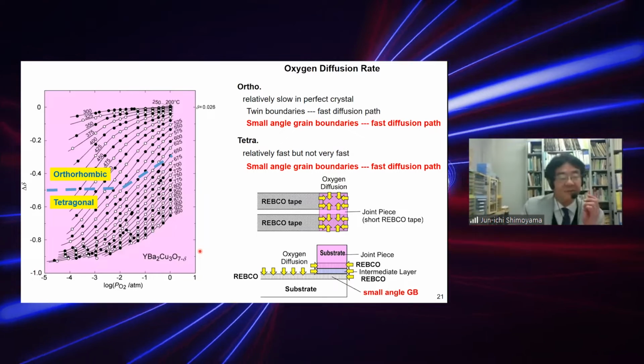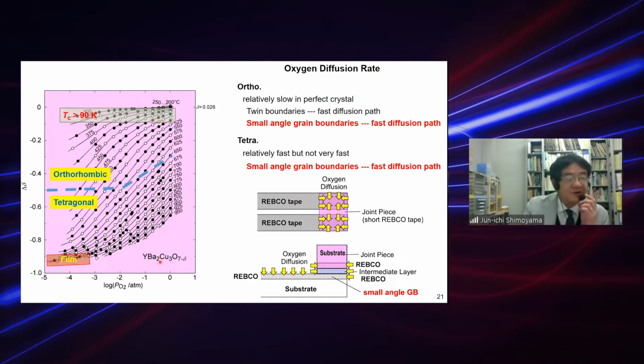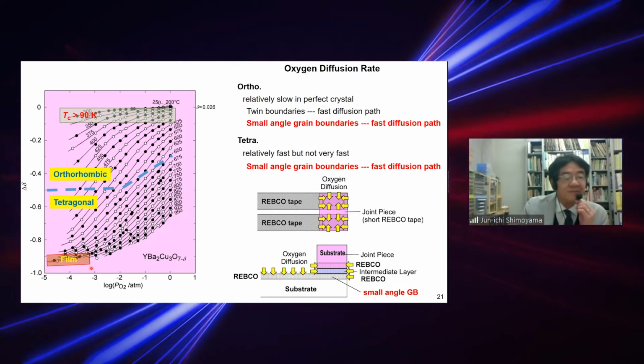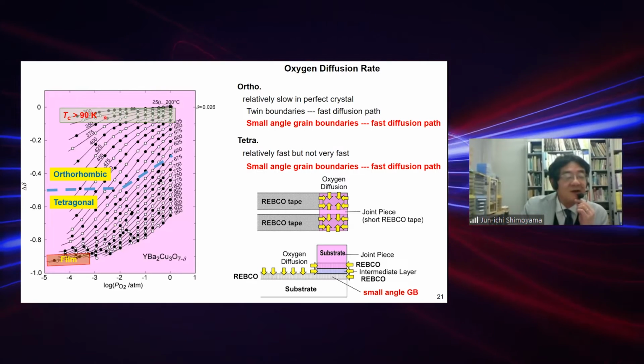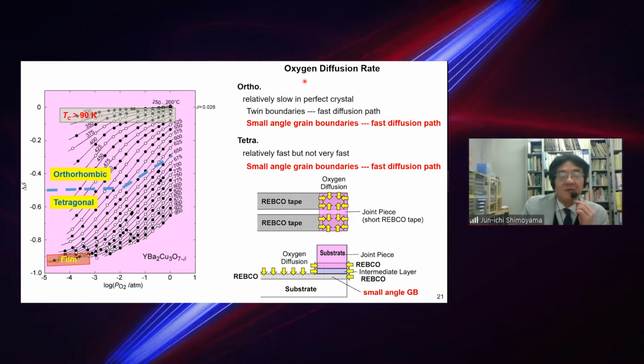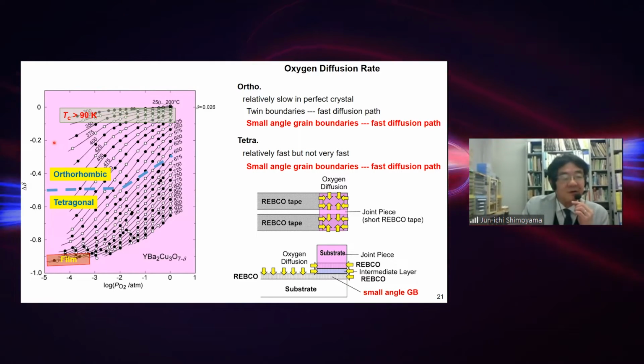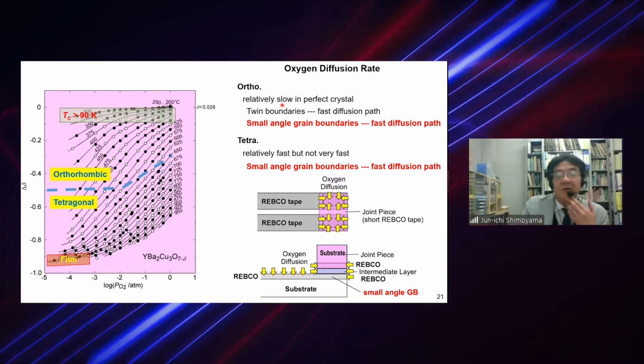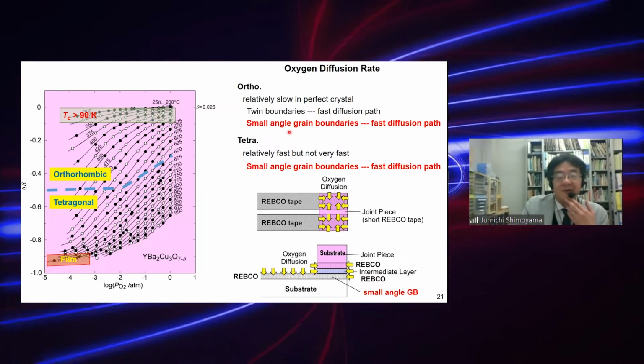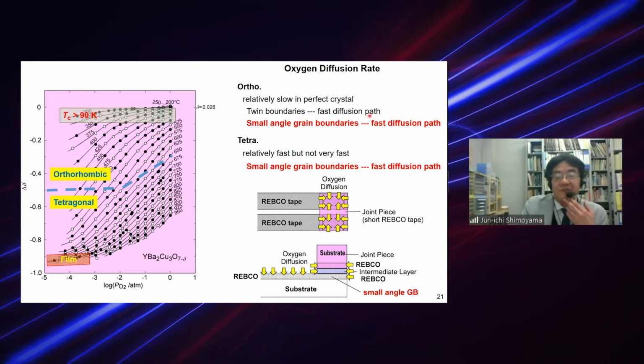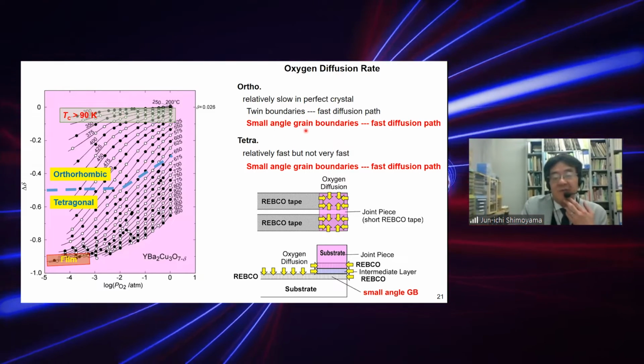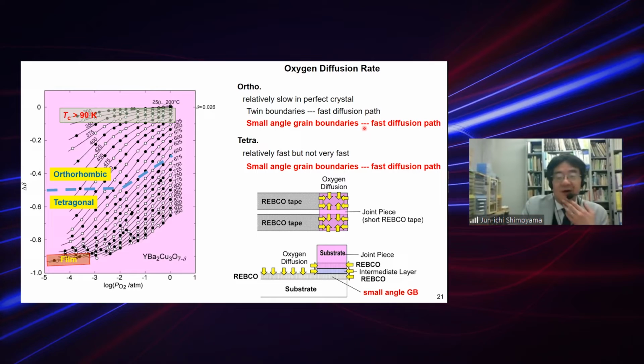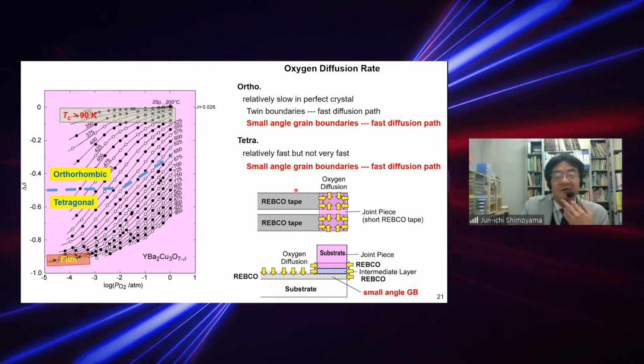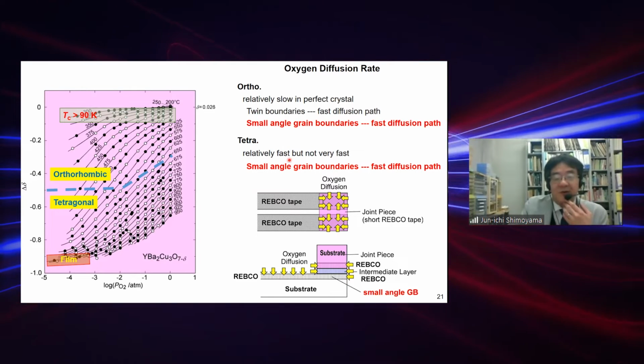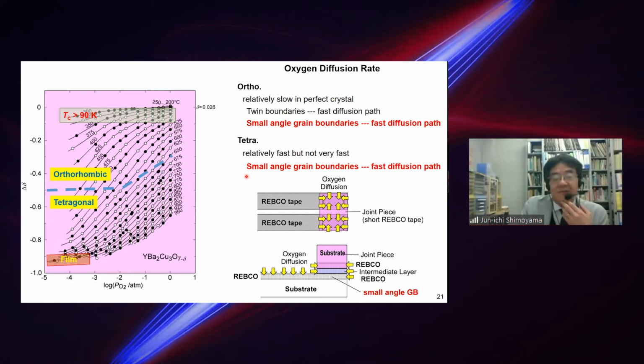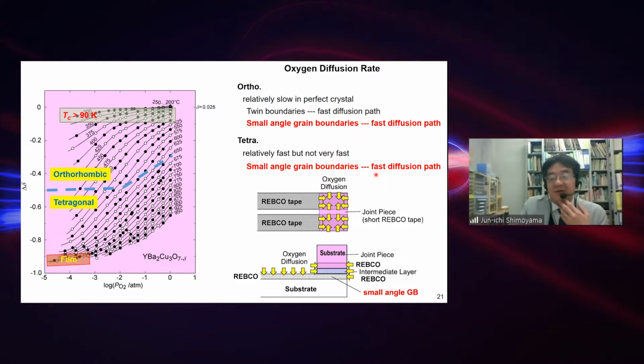When we think about the oxygen non-stoichiometry of 123 systems, this is the condition for film synthesis, in the high superconducting temperature regions. When we consider the oxygen diffusion rate in the orthorhombic region, oxygen diffusion in perfect crystals is relatively slow. However, twin boundaries can act as fast diffusion paths, as well as small angle grain boundaries in the REBCO conductors. In the tetragonal phase, oxygen diffusion is relatively fast, but not very fast. Also in this case, small angle grain boundaries can act as a fast diffusion path.